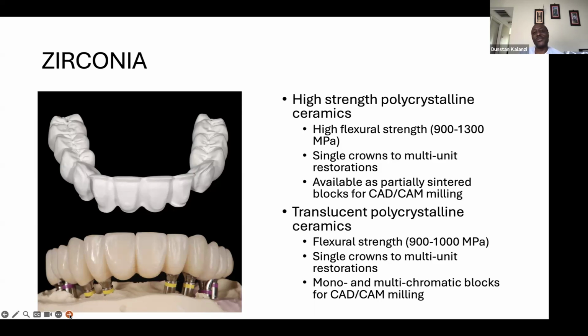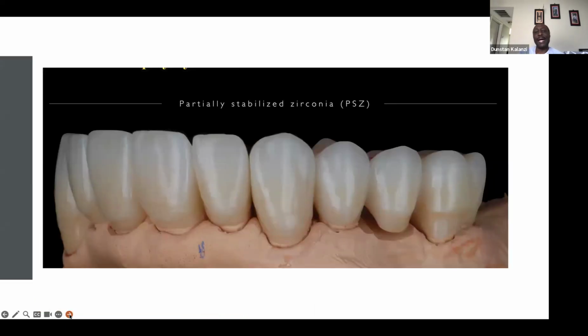So in order to get the advantage of the strength, they have tried to add things in the polycrystalline ceramics to improve the translucency. And that's why you have the translucent polycrystalline ceramics. But their flexure strength is reduced, not significantly, and they have the same applications as the high strength ceramics. And you have them coming as mono or multi-chromatic blocks for CAD/CAM milling. Normally, in the highly translucent ceramics, the volume of yttrium is increased. So they come as partially stabilized zirconia, and you can use it for your full mouth reconstructions.